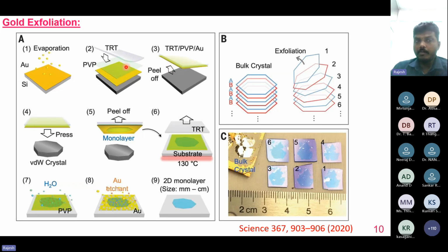At 130 degrees, by heating, this thermal release tape will be released. Then they remove the polymer with the help of water. Then finally, with gold etchants, the gold will be removed. So we are getting complete large-size exfoliated samples in the range of millimeter to centimeter size. In the right side image, you can clearly observe the exfoliated samples are almost 1 centimeter in size. Another approach of exfoliation is called liquid exfoliation.